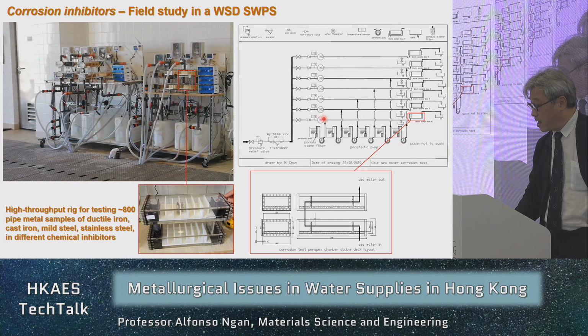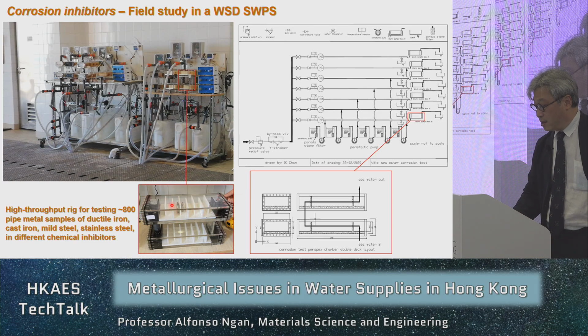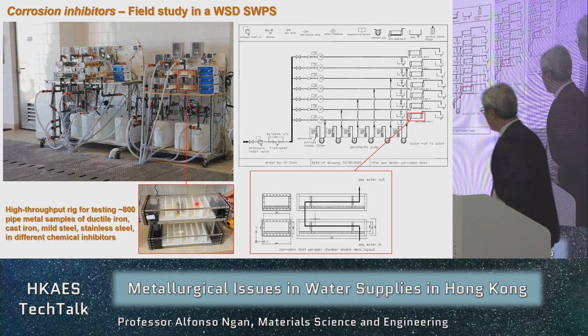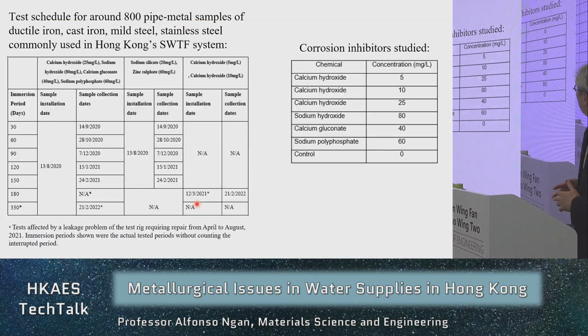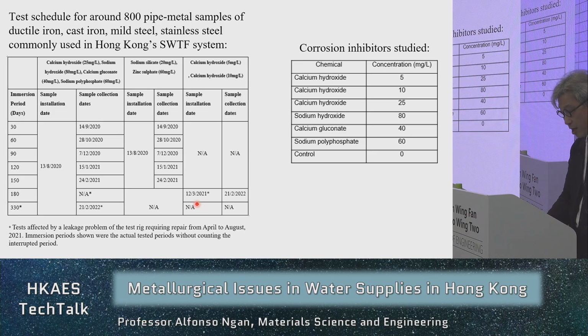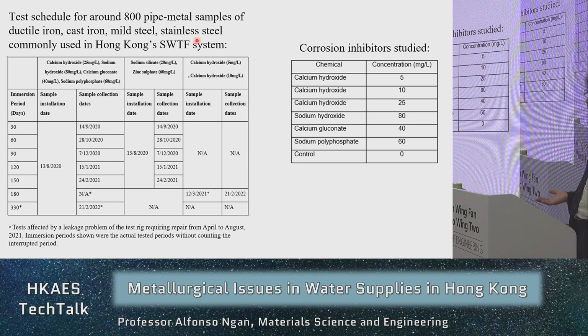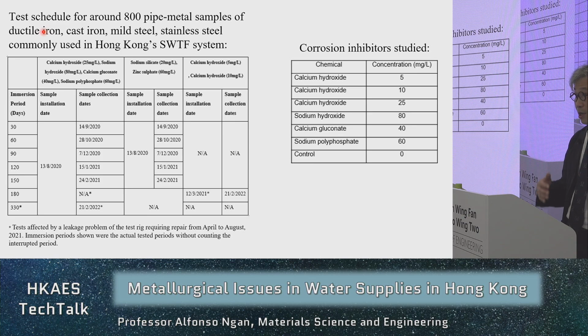And then along the pipeline, we have a certain number of these specimen holders. So there are these compartments, and in each compartment, we can mount a lot of metallic specimens. The metallic specimens are typical metals for making the pipes, including ductile iron, cast iron, mild steel, stainless steel. In Hong Kong, we don't actually use that much stainless steel because of the cost, but just for comparison, we also did that. So mainly for real applications, we use ductile iron, cast iron, and mild steel. Okay, and then that was the test schedule. As I said, the study took place during the pandemic, so it was not easy, but we managed to finish the project. So those were the immersion periods ranging from a month to, let's say, close to a year.